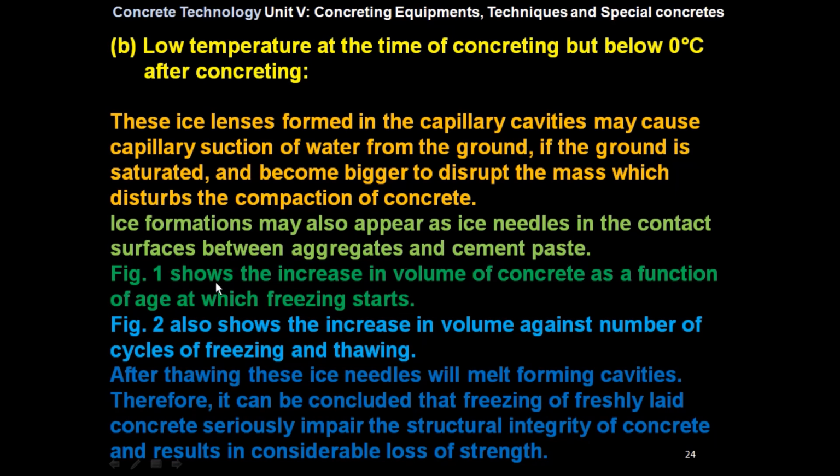Figure 1 shows the increase in volume of concrete as a function of age at which freezing starts. Figure 2 also shows the increase in volume against number of cycles of freezing and thawing. After thawing, these ice needles will melt, forming cavities. Therefore, it can be concluded that freezing of freshly laid concrete seriously impairs the structural integrity of concrete and results in considerable loss of strength.